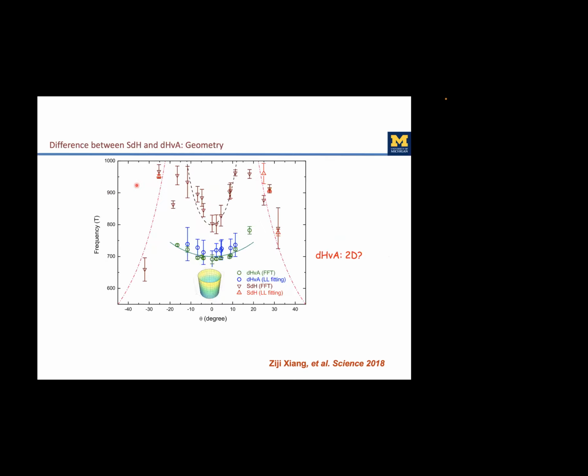The angular dependence is puzzling, as I emphasized. Some torque data gave me something like a cylinder-like Fermi surface. Maybe cubic, but whatever, that might be a good fit. But bottom line, for resistivity, SdH oscillations show a hyperbolic dependence, which means I'm having a narrow neck that's touched by 2 hidden Fermi surfaces. That's very strange, and tells us that if we do something really well, we may even be able to observe that hidden orbit size.